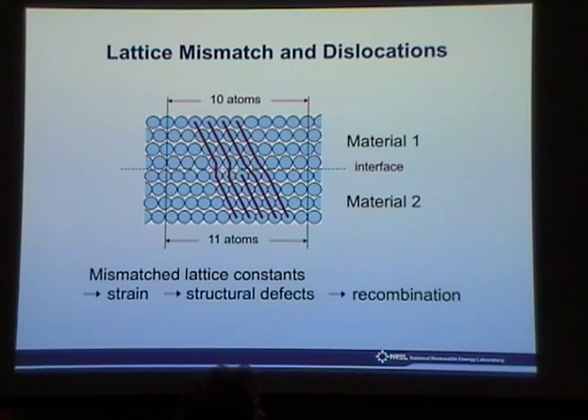So if you look carefully, there's a half plane in material 2 that terminates at a dislocation. If you follow these red lines up, there's an extra half plane right here. So that's a dislocation that has mediated the strain relief, but that dislocation itself is essentially a set of dangling bonds. And that is a prime site for non-radiative recombination, by which you end up losing electron-hole pairs.